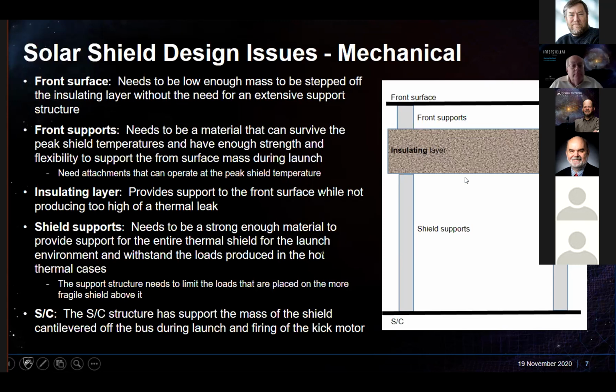You get back to the insulating layer. The insulating layer, again, has to support everything above it. So it's supporting the front surface and all those supports as a structural element. Again, one of the big issues on Solar Probe was, if you're using a carbon-carbon foam sandwich kind of material as a structural element, that does really well from an insulation point of view, but it doesn't have a whole lot of strength to carry large loads into it.